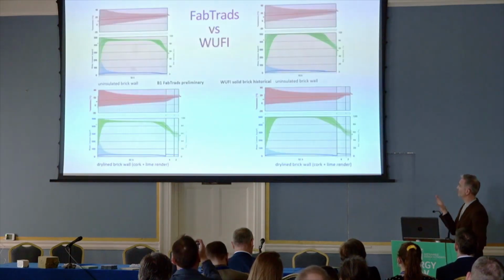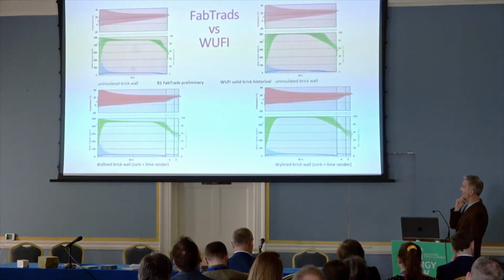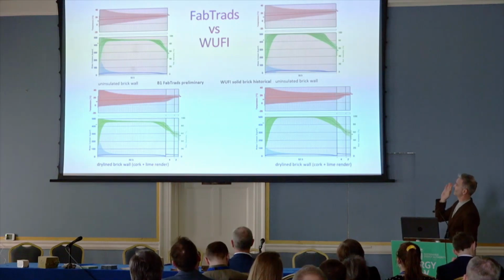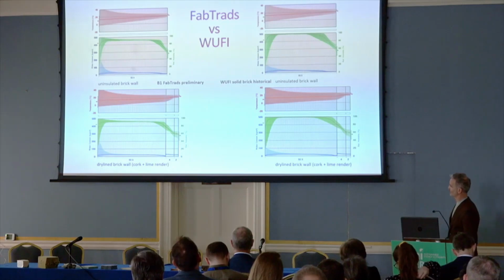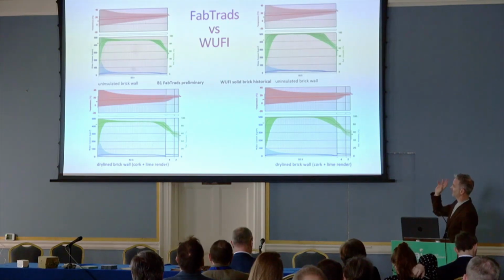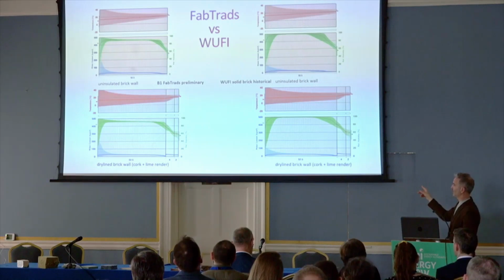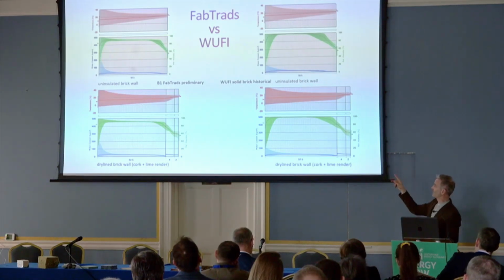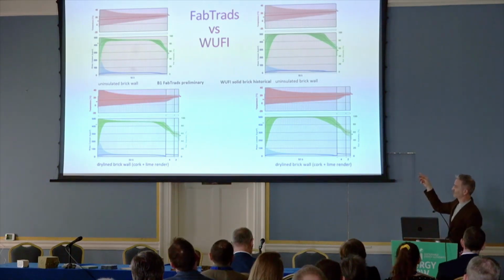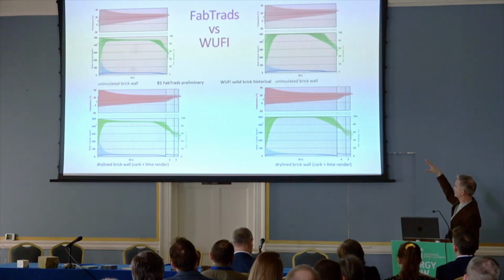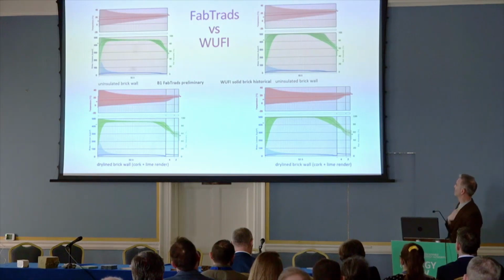And here are just some very early results from WUFI analysis that we've done, showing in this case the difference between the simulations using the Fab Trads range of parameters versus the WUFI range of parameters. So I should just explain these graphics. The outside is on the left of each of these walls. These are sections through wall build-up. In the top case, it's an uninsulated solid brick wall. In the bottom case, we've added insulation and render in both cases.